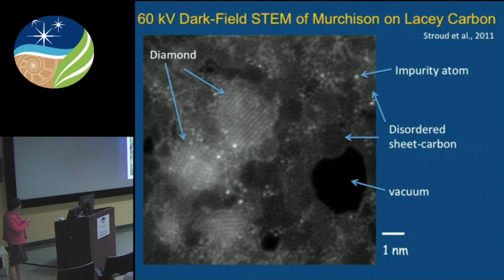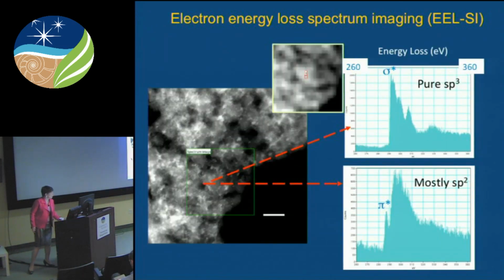Today's scanning transmission electron microscopes actually let you go in and look not at the atomic plane resolution, but down to the single atom resolution. So this is an image I obtained at Oak Ridge National Lab before getting my own aberration-corrected STEM, in which you can resolve single atoms and single layers of carbon. So this is a single sheet region of the image where you can resolve the ring structure of the disordered carbon.